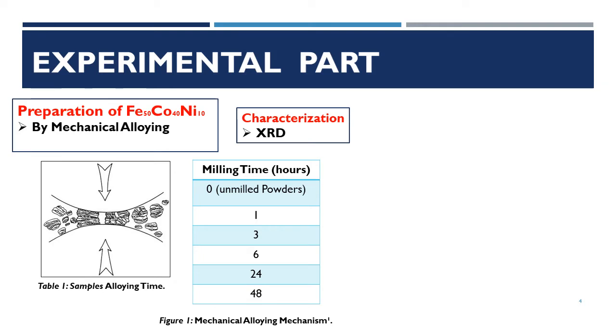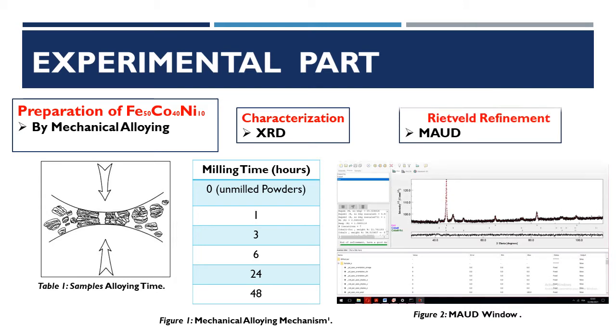We used the X-ray diffraction technique to examine the phase evolution and the structural parameters of the alloyed samples as a function of milling time. Those parameters were revealed via the refined X-ray diffraction data by the Rietveld refinement using the MAUD program version 2.99, as shown in figure 2.